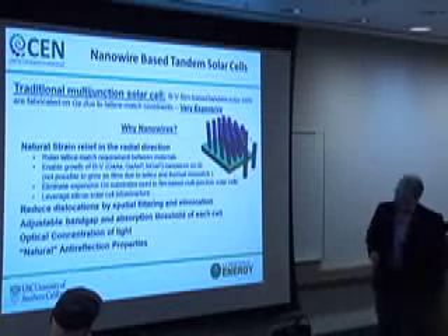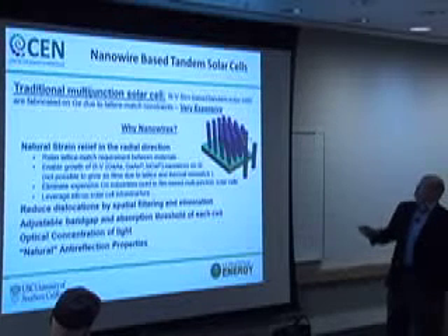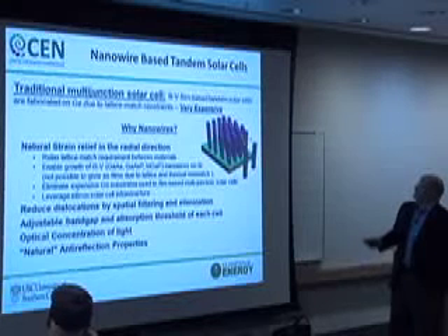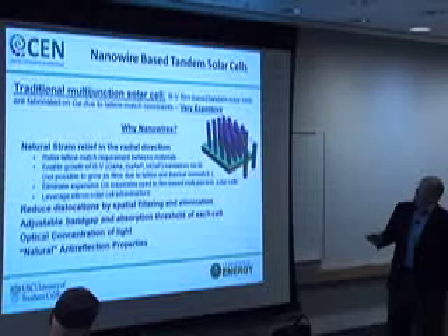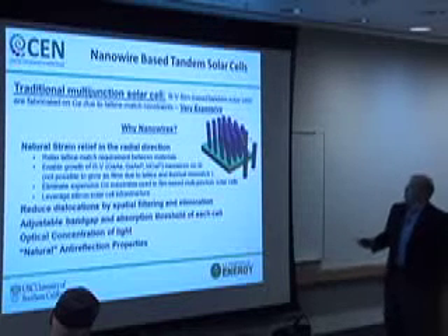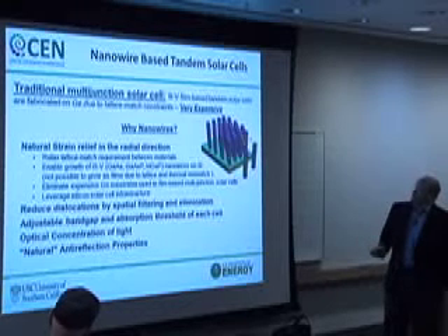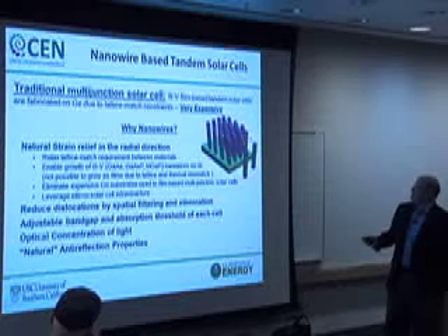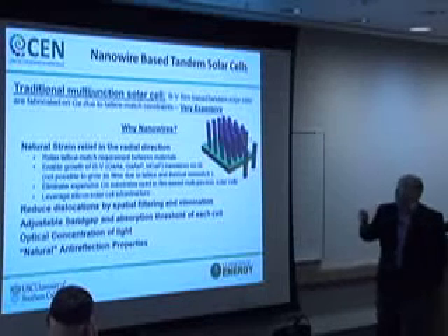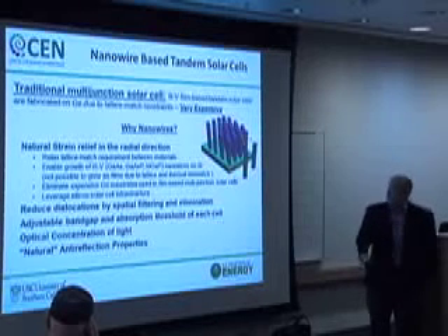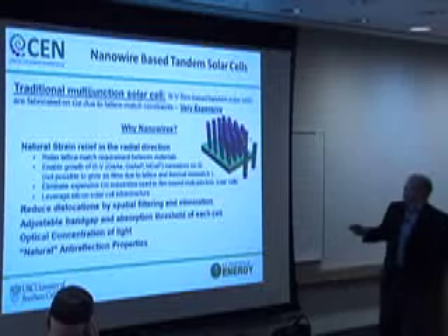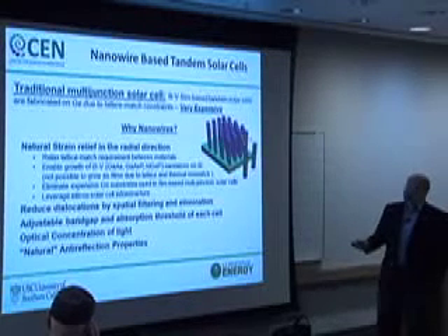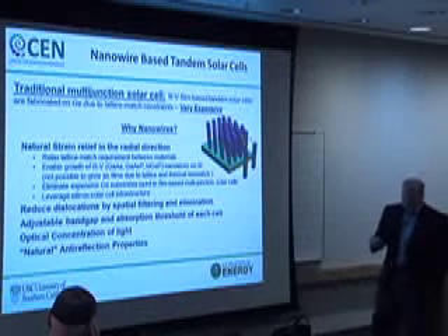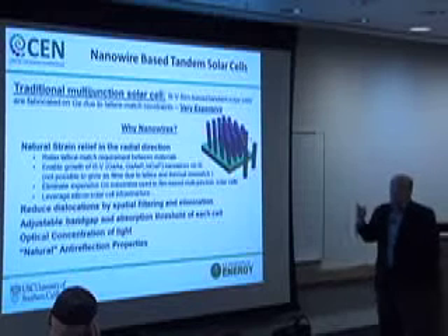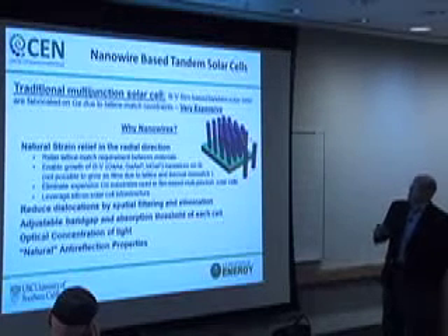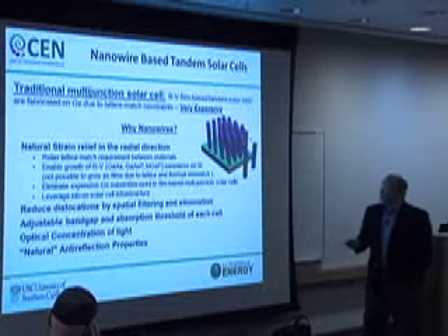And the approach that we're using is to replace the epitaxial thin films with nanostructures. In this particular case, nanowires or nanorods, depending on what you might want to call them. And the idea here is that because the dimension of these materials can be architected so that they're very small in a lateral dimension, you have the possibility of growing these things on a lattice mismatched substrate without getting the dislocations that typically occur at lattice mismatched interfaces propagating into the material. And that's sort of a fundamental idea behind why we're trying to do this.